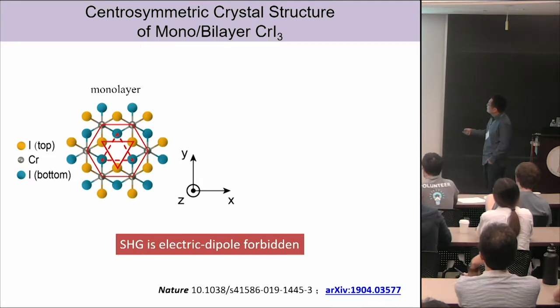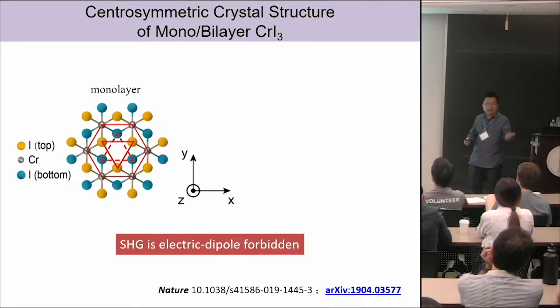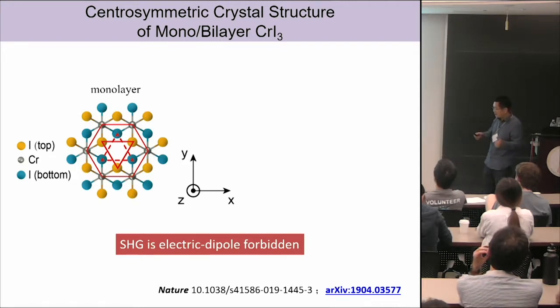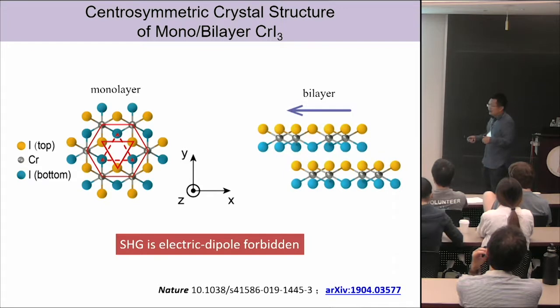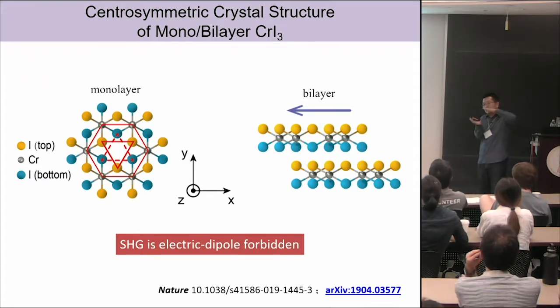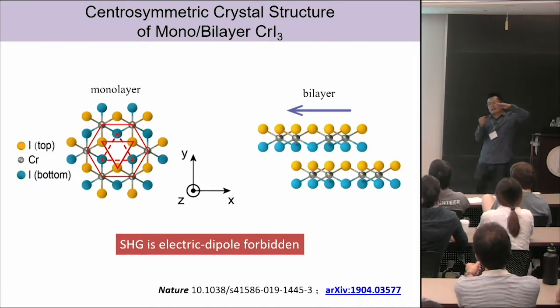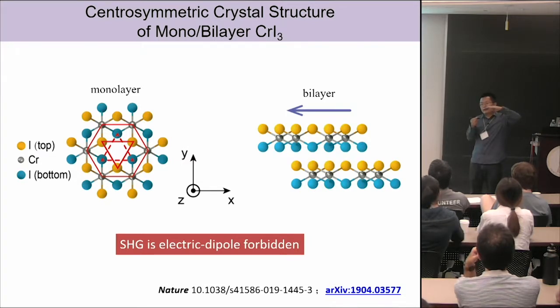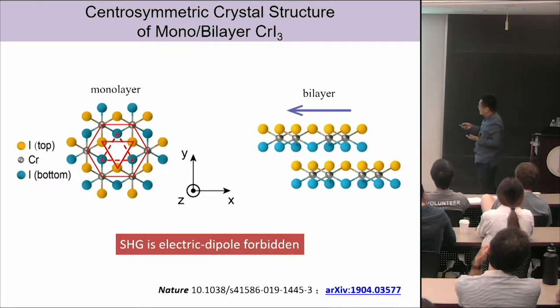In the monolayers, it has this D3d crystal symmetry. It actually has an inversion symmetry, so there's no second harmonic generation. And in a bilayer, when these two crystals align in the same direction, no matter how you slide them, right? Because the monolayer is already centrosymmetric. If you put another layer on, you can just convince yourself, if it's also in the same orientation, no matter how you slide them, the central symmetry doesn't break. Okay. So the bilayer is also centrosymmetric, and the second harmonic generation is an electric-dipole forbidden transition.